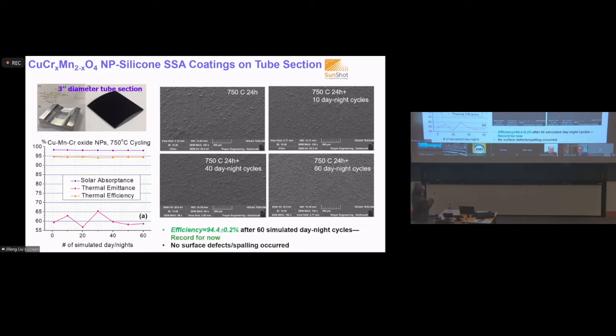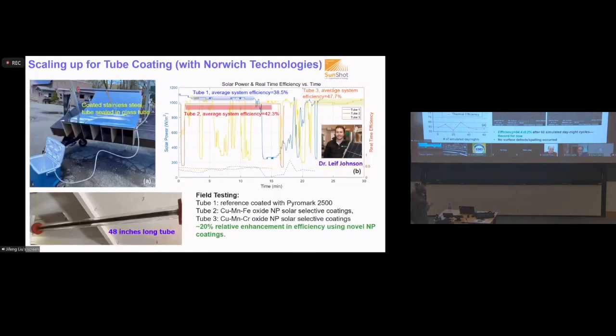In this case, you can see this is 24 hours at 750 degrees. This is 24 hours after 10 day-night cycles, 40 day-night cycles, 60 day-night cycles. Essentially, there's no spalling on the surface. The surface looks good. Look at the efficiency, it keeps high, about 94% all the way across. That's essentially a very successful coating development here.